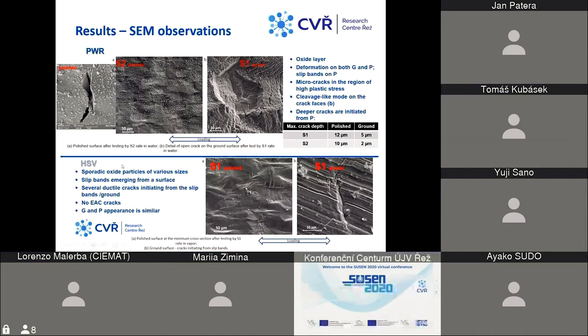On the other hand, on the specimen after hydrogenated steam vapor testing, we found only sporadic oxide particles of various size on the surface. On both surfaces, we also found the slip bands emerging from the surface on the polished and the ground side, and we found only several ductile cracks initiated from the slip bands, basically only on the ground side of the sample, and we didn't find any environmentally assisted corrosion cracks. Basically the ground and polished appearance is similar after this testing.